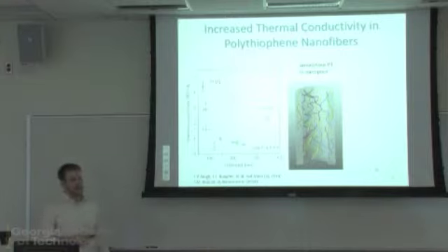Just to make it clear, the polythiophene nanofibers you're talking about, were these electrochemically prepared? Yes, these are electrodeposited in an AAO template. So then, did you reduce them, or are those the oxidized form that you're measuring? Reduced. How did you reduce them? We de-doped them through the KOH, I believe. Yeah, it's reduced through the chemical processing, after electropolymerization when you wash them with KOH, so most of the dopant is out. So when we measure the electrical conductivity, they are insulating.